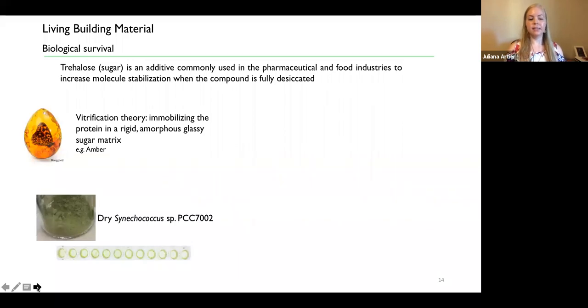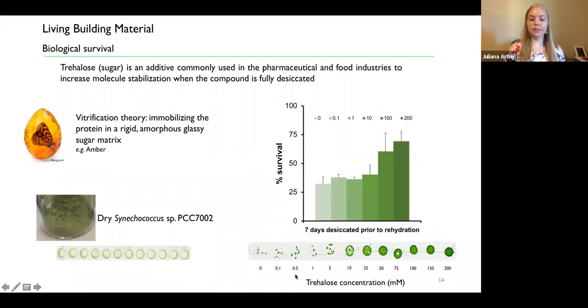So what we did here, we dried the cells, just the cells for initial tests to see how we could improve the biological survival under desiccation from this bacterium. And we added increasing concentrations of trehalose, and we saw that once we reached about 200 millimolar in our cells, we were able to highly increase the survival compared to when we don't have any trehalose being present.